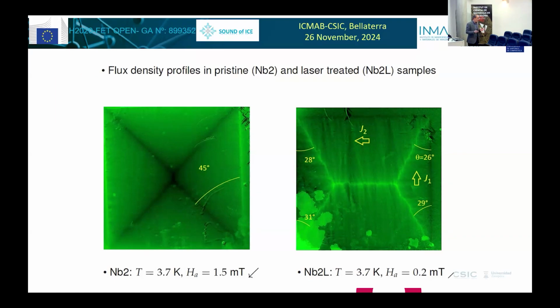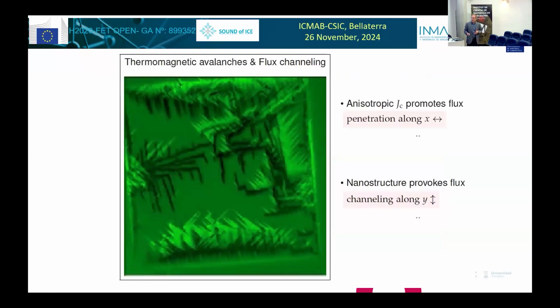So we change completely how this works. And this is essentially what we see: there's an anisotropic JC, which promotes flux penetration along one direction, which is perpendicular to the LIPS that we made, these nano-ordered structures. And this nanostructure provokes flux channeling along these LIPS, these nanostructures. So the nanostructures are in one direction.